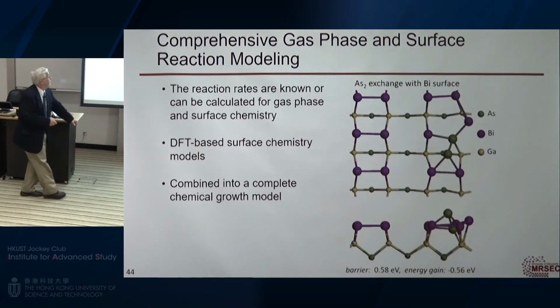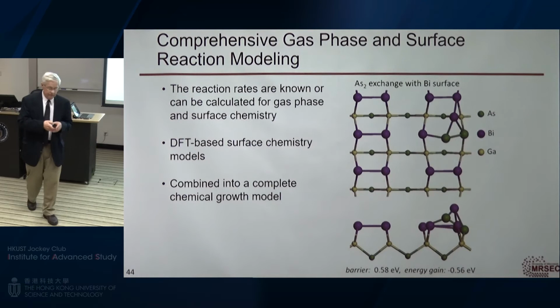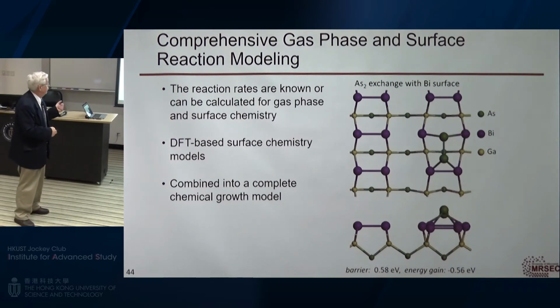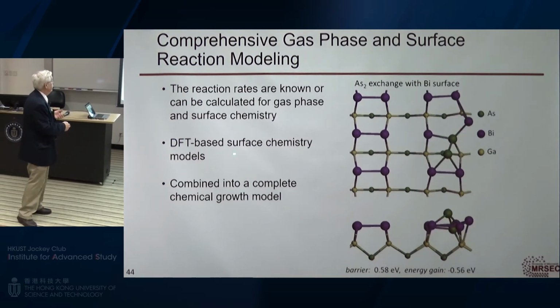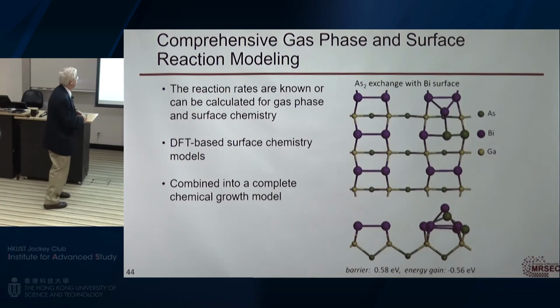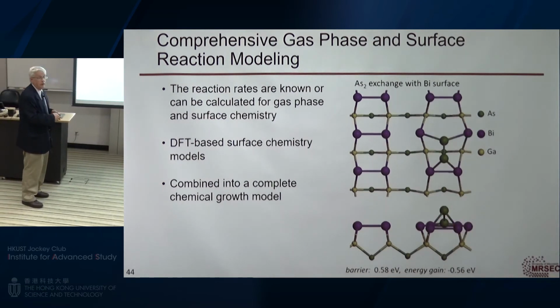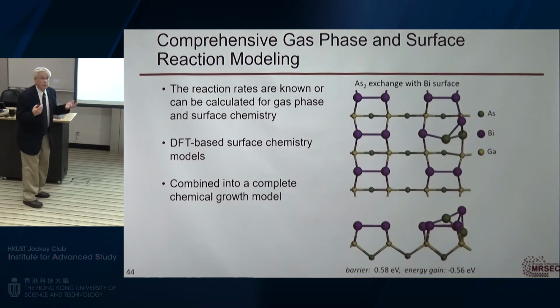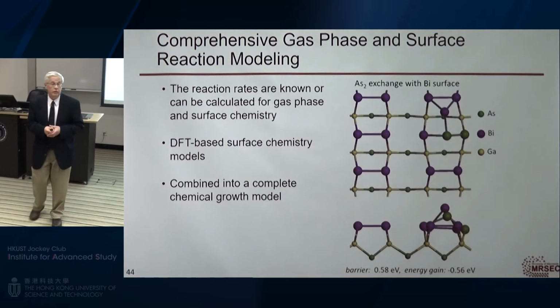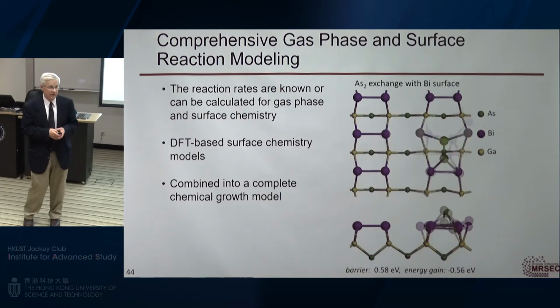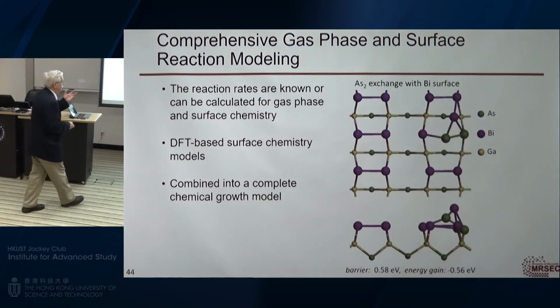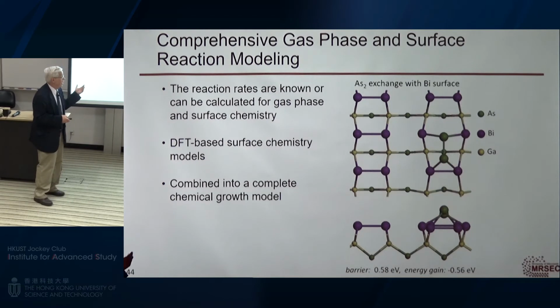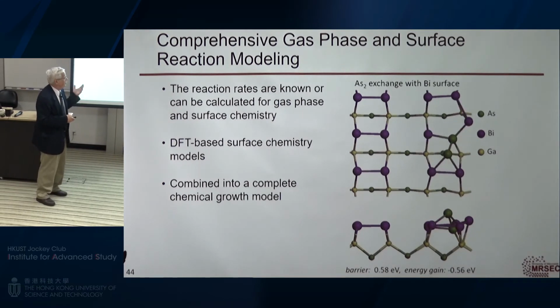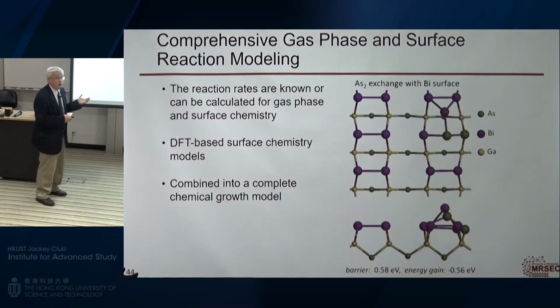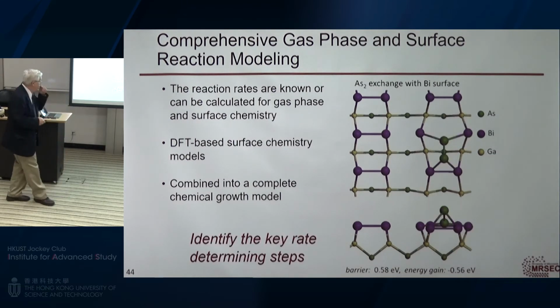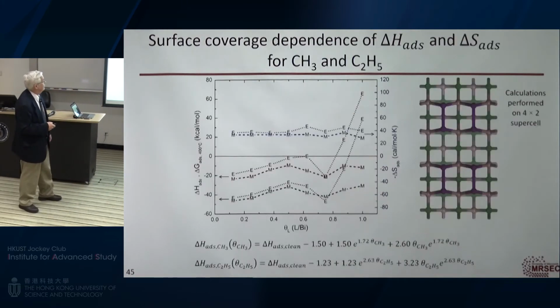So what we did is we took every one of those reactions and either from the literature or we used density functional theory to look at the reaction rate. And then we combined these into a complete chemical model. There are probably about 20 to 30 relevant chemical reactions happening in the gas and the surface. A lot of them have been measured, but the ones that haven't been measured, particularly the ones on the surface, we can compute. And we can identify the key rate determining steps.